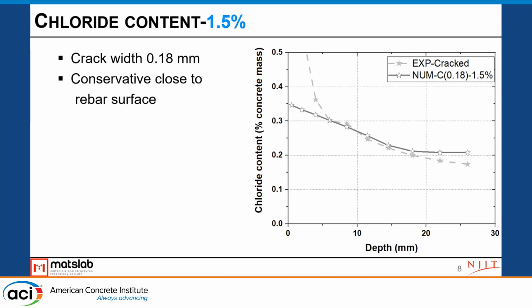We may notice in the first layers close to the surface, the numerical result underestimates the experimental test. This is because close to the surface, it is a convection zone, which is kind of tricky. But our concern is really about the chloride contents close to the steel surface. For example, we see here up to 26 millimeter, where the rebar is located, we have a pretty close chloride prediction to what we get in the test, and it is also conservative.